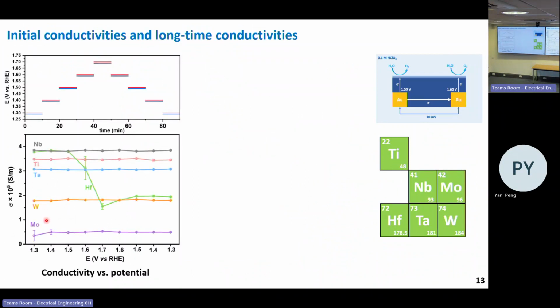So we've tested all of these 6 metals, and some metals like tungsten and molybdenum seem to have formed the oxide layer already at 1.3 versus RHE, and the hafnium is quite stable until 1.6, and this corrosion seems to be irreversible even when we scan back to 1.3.